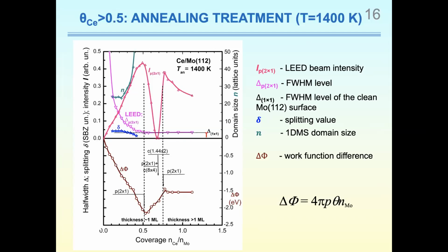Yeah, that's correct. So the metallic cerium has a lower work function than molybdenum, and so the deposition of cerium on molybdenum decreases the work function. I don't remember the exact value for clean cerium. We are talking about a bimetallic surface, so it's a mixing of atoms which gives us a new value of work function. The pure metals eventually will demonstrate just the intrinsic work function because of the position of the Fermi level, yeah?